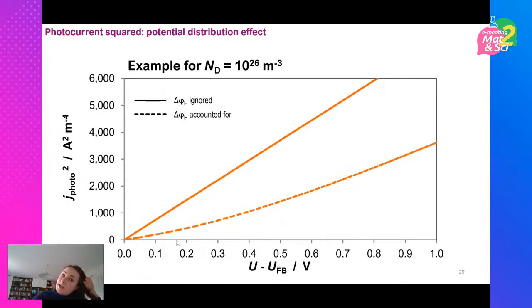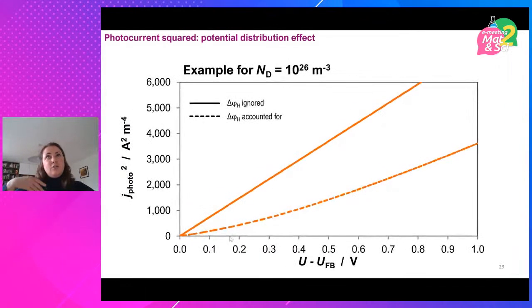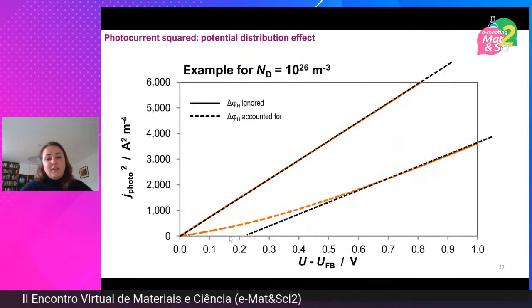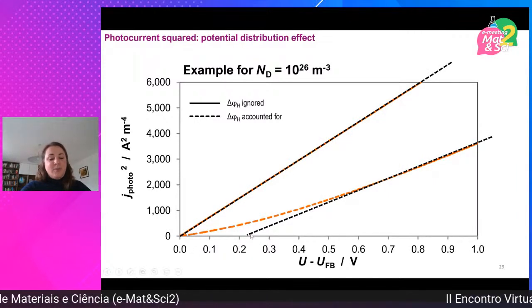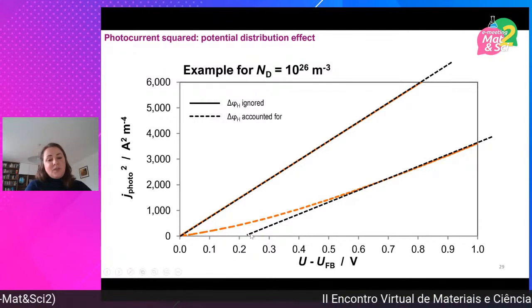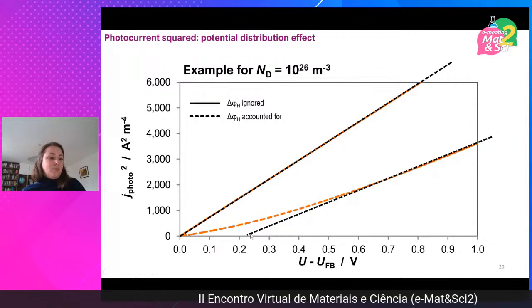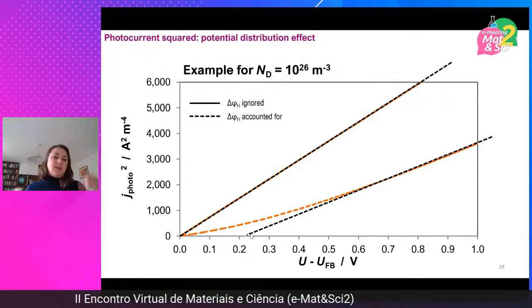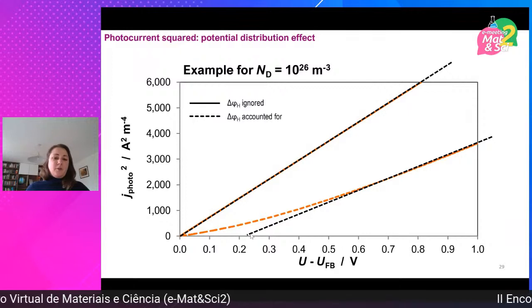And just to illustrate that, the Gärtner-Butler equation from which this technique was actually derived also assumes that there's no potential drop across the Helmholtz layer. And if you were to introduce that, the kinetics look very, very different. And if you were to account for the Helmholtz layer, which is what you have when you look at your experimental data, you can see that the shift in the determined flat band goes in the positive direction. So in the case of Mott-Schottky, you get overly negative values, and in the case of this photocurrent squared, you get overly positive values.